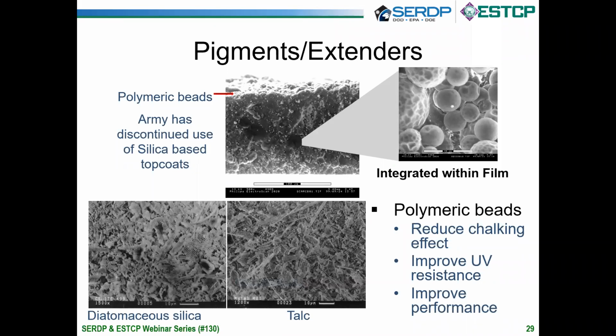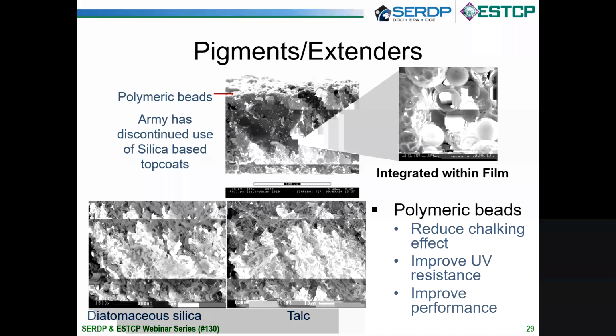The next, I'd like to highlight the pigments and extenders. As I'd mentioned, we introduced polymeric flattening materials. And this SEM beautifully shows how the beads integrate within the film. Being a similar composition for the system, it greatly improved MAR resistance, UV, reduced chalking effects. The result is that our top coats are predominantly flattened using polymeric beads, and this goes through virtually all of our systems that are in play today.